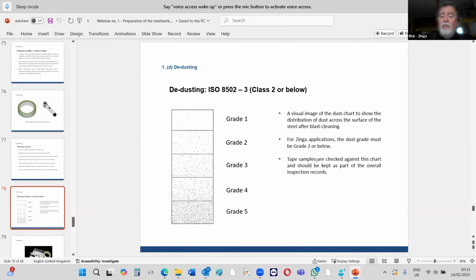If you have grade 3 or grade 4 dusting with any coating, not only Zinga, if you spray it on, it's potentially going to stick more to the dust than to the metal, so you don't have a strong adhesion. This is why you want to remove the dust, so you're sticking straight onto the steel itself, with nothing in between.